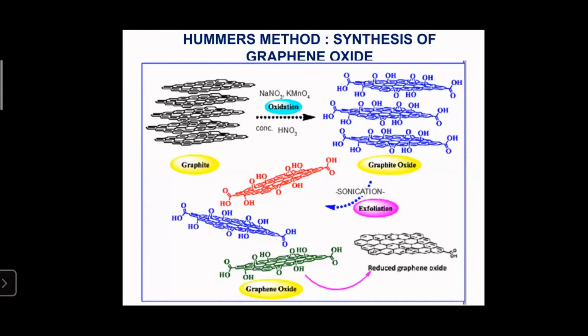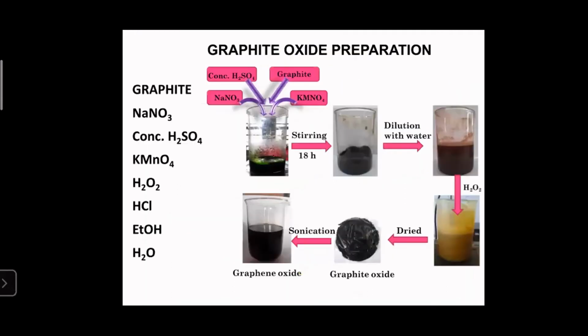For the production of graphene, this graphene oxide is then reduced by various means. And we get graphene, usually called reduced graphene oxide, because some of the functionalities remain there. In addition, there are lots of defects on this reduced graphene oxide. So the conductivity and the regain of the aromatic network is not so possible in reduced graphene oxide. But the functionalities of reduced graphene oxide allow the incorporation of various species between the graphene layers.